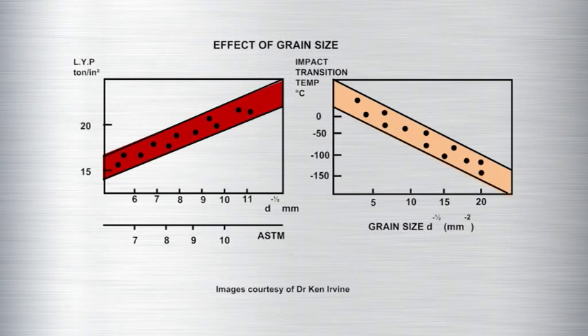So, armed with about 100 data sets of structure and properties, we commenced the statistical analysis using regression techniques, and there were some very interesting results came out of this. Firstly, if we looked at the effects of grain size particularly, then grain refinement was the only mechanism really which improved both the strength and the toughness simultaneously. In all the others, there was some disadvantage to the toughness if you increase the strength.